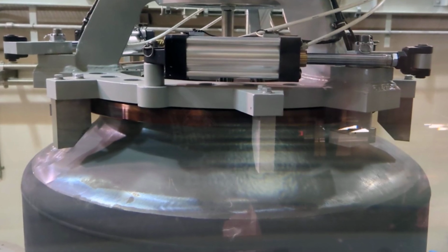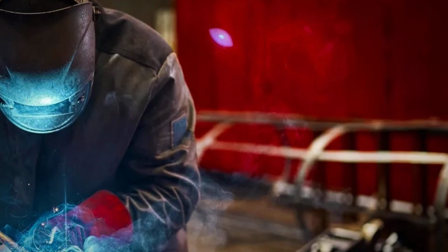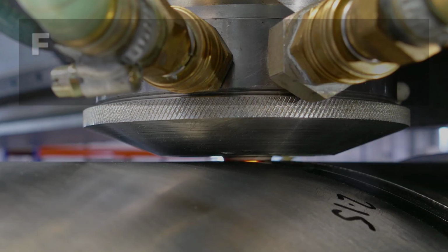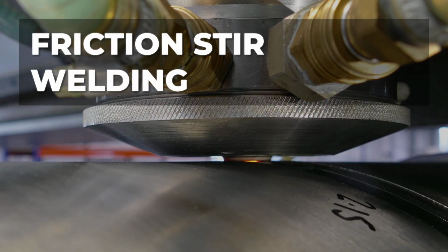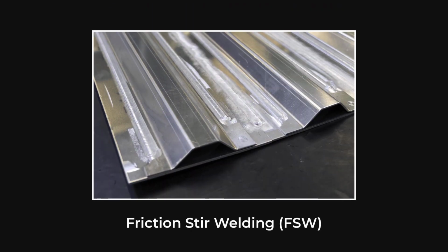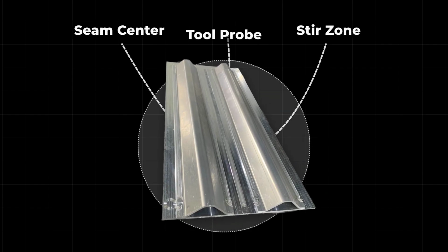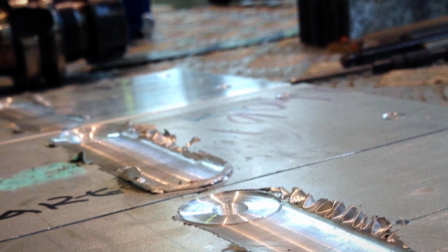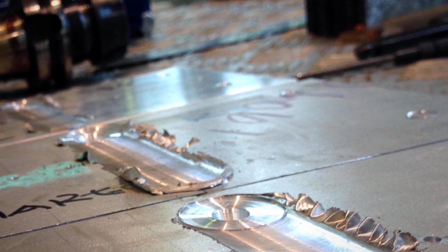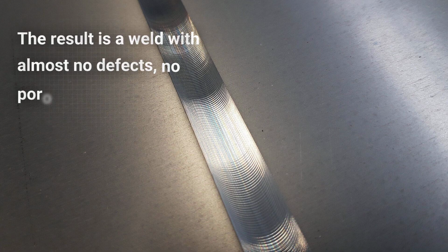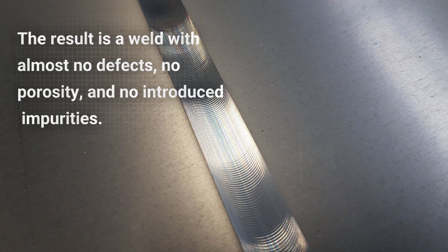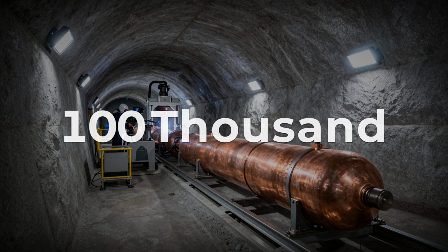Once a canister is filled, the lid has to be sealed. This is where one of the more elegant engineering choices comes in. The seal is created using a technique called friction stir welding. Originally developed in the 1990s for joining aerospace aluminum, friction stir welding doesn't actually melt the metal being joined. Instead, a rotating tool plunges into the seam between two pieces of copper, generates heat through friction, and stirs the softened metal until the two pieces become metallurgically continuous. The result is a weld with almost no defects, no porosity, and no introduced impurities. For a container that has to stay sealed for 100,000 years, conventional welding wasn't good enough.